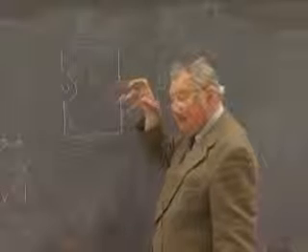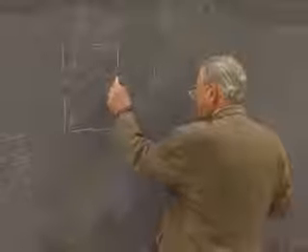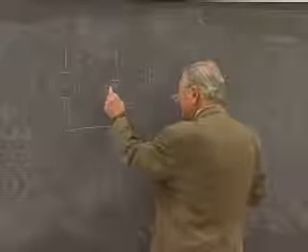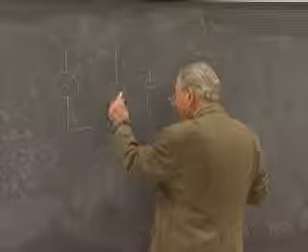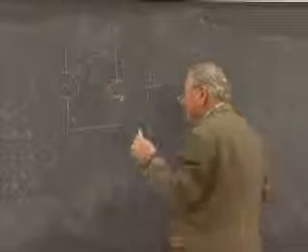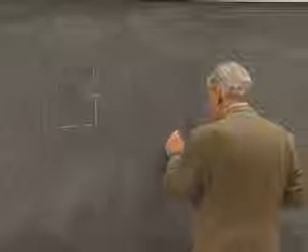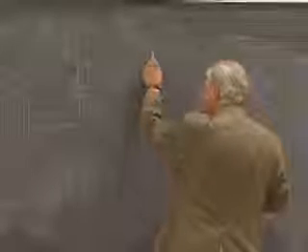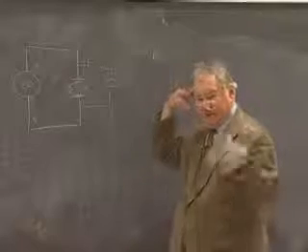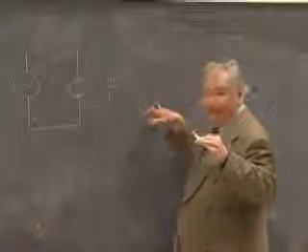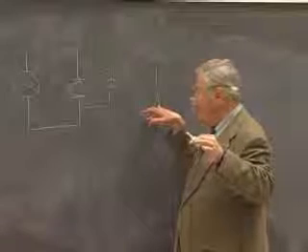And if we would do that by having this variable frequency generator, as we turned it, when we hit a resonant frequency that set up either a full wavelength of a vibrational wave in the crystal, or one half wavelength, or one wavelength, or 3/2 wavelength, there'd be a resonance, and the capacitance does something crazy. It does like this as you go through the resonant frequency. And in your simple detector, a pair of earphones, as you tuned the frequency, you would hear static as you went through this discontinuity in capacitance.